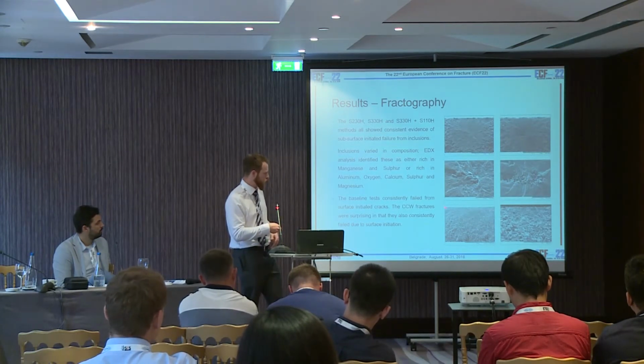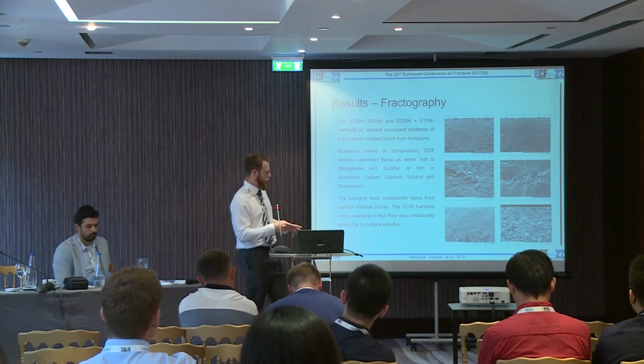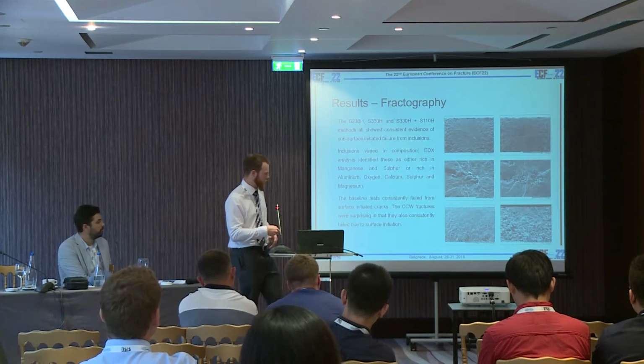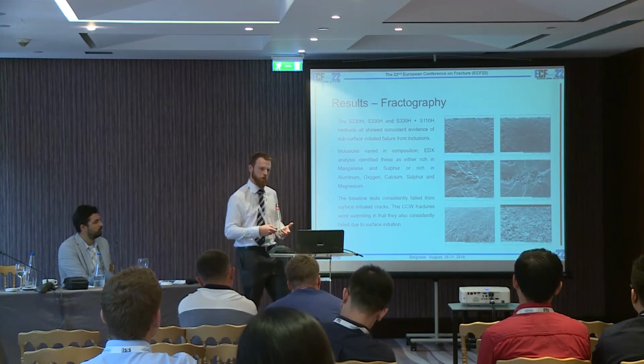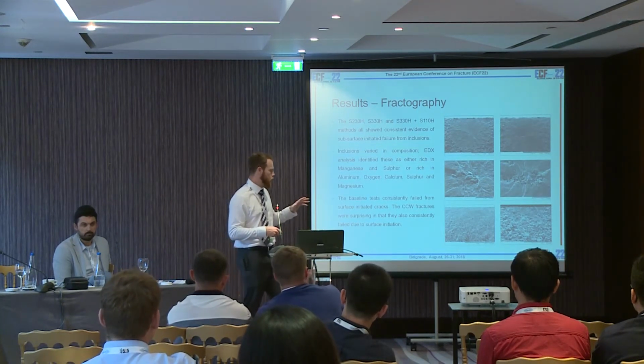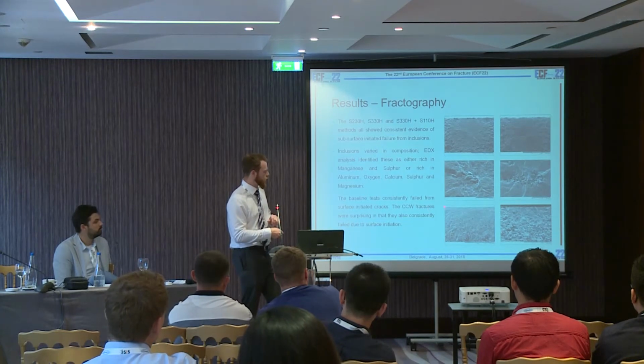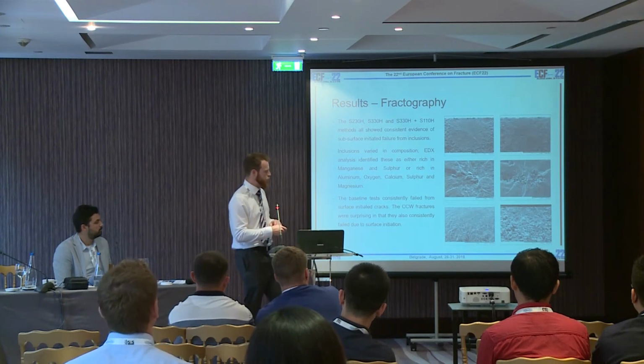The baseline steel, as we would expect, consistently failed from surface-initiated fractures, and these were generally from intergranular oxidation, as I said, from the gas carburizing process. So finally, I think the one, again, of most interest is the condition cut wire process. All of these fracture faces that were analysed all showed surface-initiated fracture rather than subsurface-initiated fracture, which isn't what we would have expected for the shot peening process. The only caveat to that is that from the manufacturer that was involved, the condition cut wire gears and the baseline gears were certainly forged from the same batch. The others were taken from a different batch, so perhaps that gives us some reason for why that occurred.